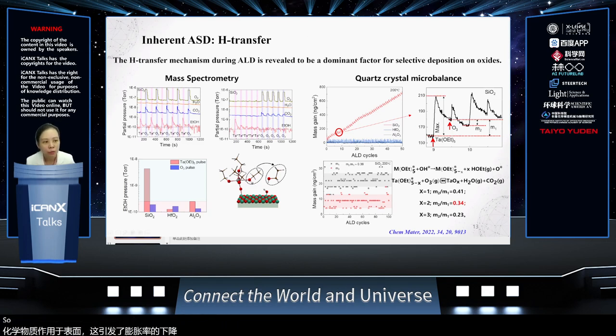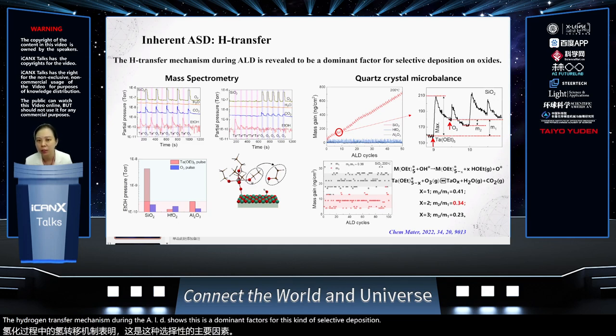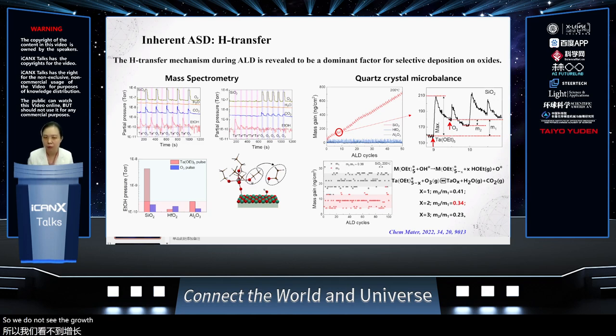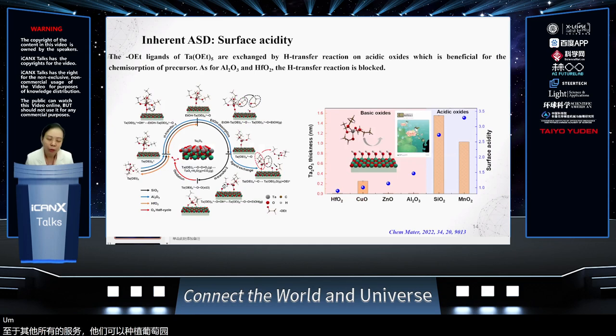So these two studies give us a pathway for how this happens. The hydrogen transfer mechanism during the ALD is a dominant factor for this kind of selective deposition. For the aluminum oxide and hafnium oxide substrates, the hydrogen transfer reaction is relatively blocked, so we do not see growth, and we get selective deactivation. For all the rest of the surfaces, they can grow linearly. To verify this mechanism, we ran density functional theory calculations with collaborators in other groups.